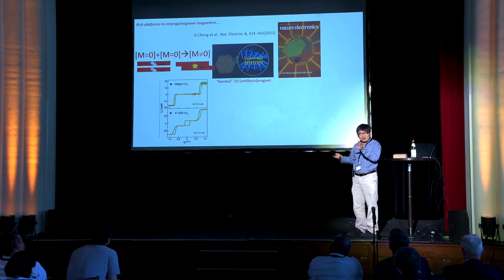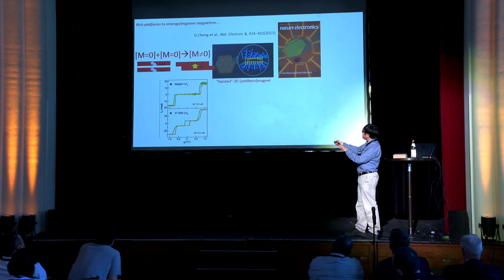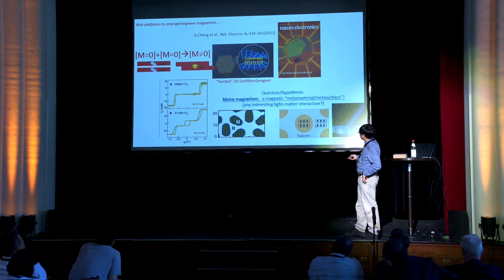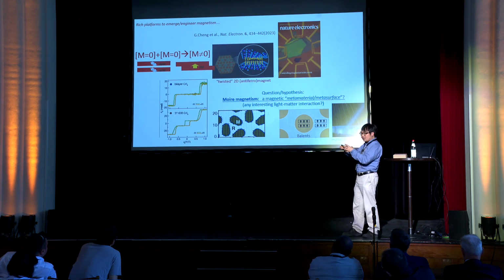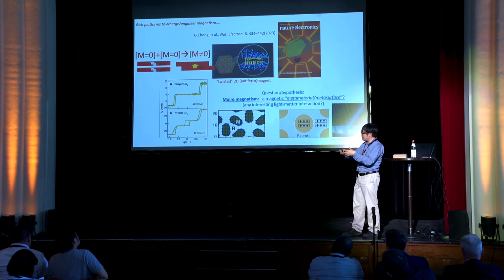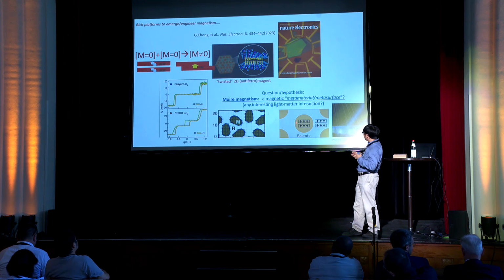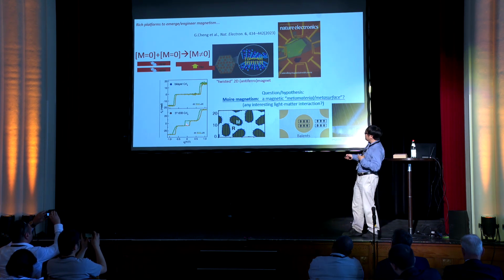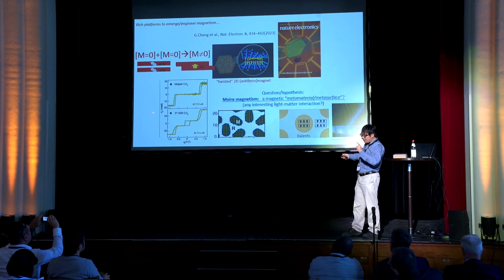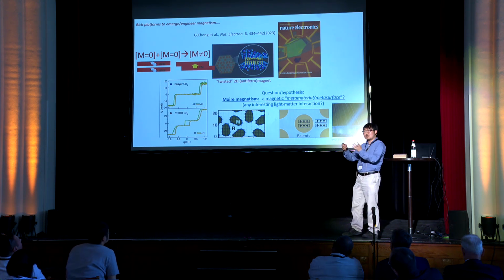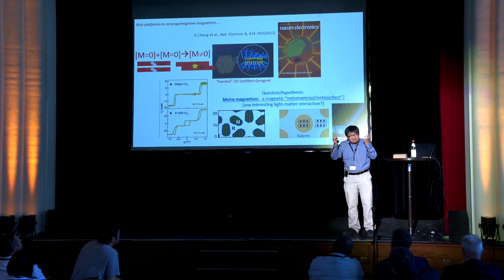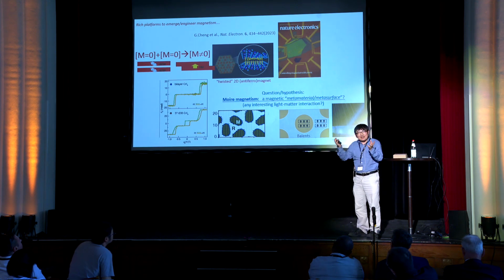In fact, there are a lot of photonics experts here, so I'd like to pose a question. This system is basically not only 0 plus 0 is non-zero, but you created this spatially modulated, almost periodic, sub-optical-wavelength periodicity, 10 nanometer region between ferromagnetic region and antiferromagnetic region. The ferromagnetic region, of course, has the finite Kerr rotation of the linear polarization of light. The antiferromagnetic region has no Kerr rotation. So this reminds me, at least, of some kind of metamaterial for magnetism.